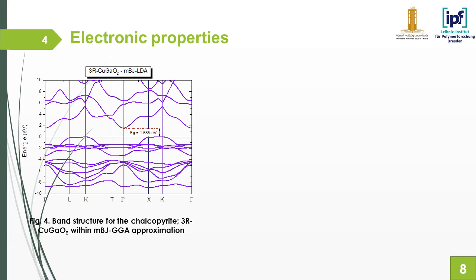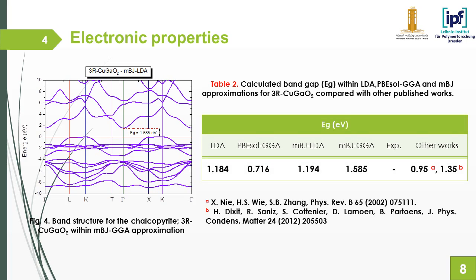In this slide, we have calculated the band structure of our delafossite oxide along various high symmetry directions in the first Brillouin zone, BZ. It is obvious that this oxide is a semiconductor material with an indirect band gap. By the way, table number 2 summarizes the calculated band gap within the LDA, PBEsol-GGA, and mBJ approximations for copper gallium oxide, compared with other previous works.